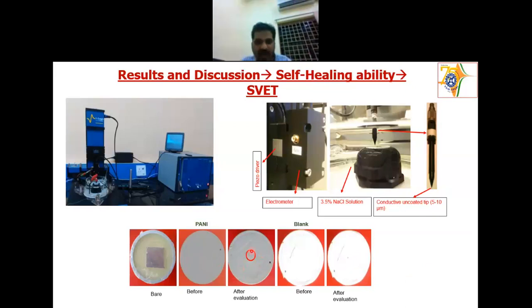The defect we make on the coating, and this is where the specimen has to go. This is a more enlarged view. You can see the sample here, and the probe is here, with an uncoated conductive tip. The size of the tip will be 5 to 10 micron, and that will be the sensitivity of the tip also. Using a piezoelectric driver, it can move in the XY and Z directions. It will move like this, scan a small area, and find out the potential difference across it, or map the current. From the current, one can say whether corrosion is happening or not. So when you make a small defect on the coating, the defect is made in such a way that the metal surface is exposed.